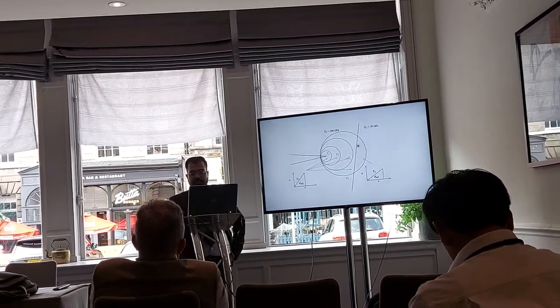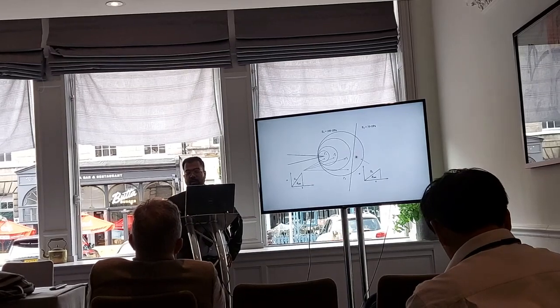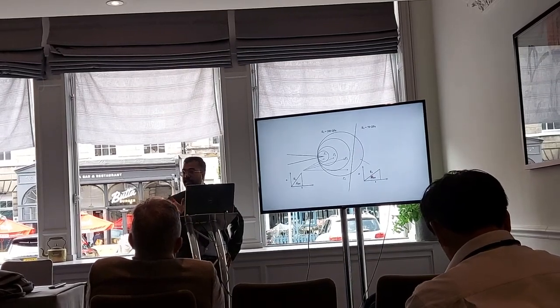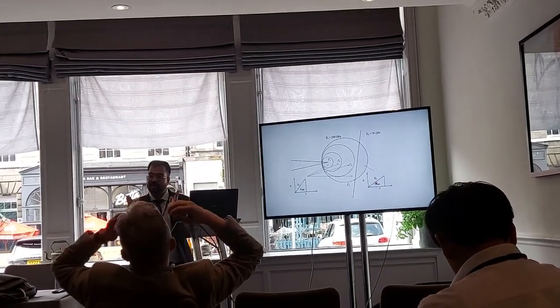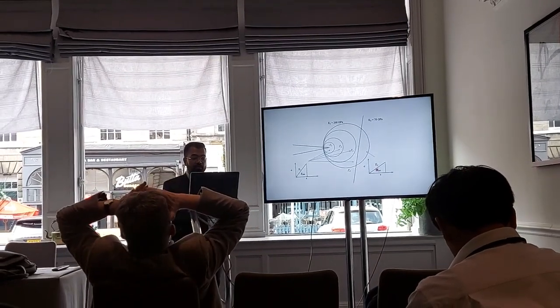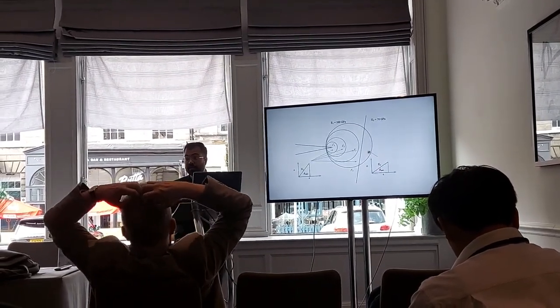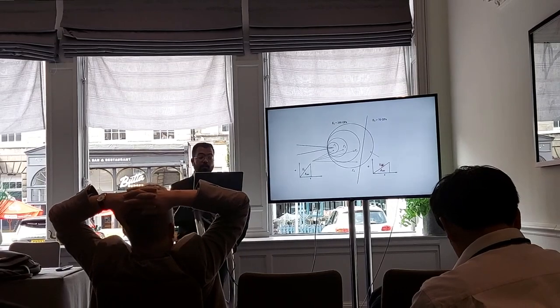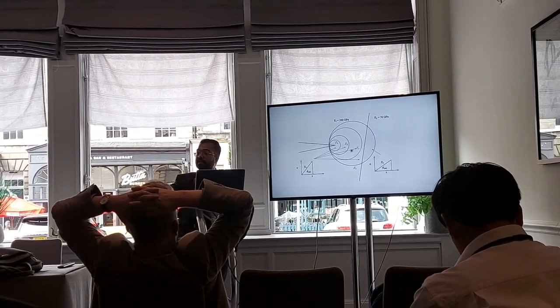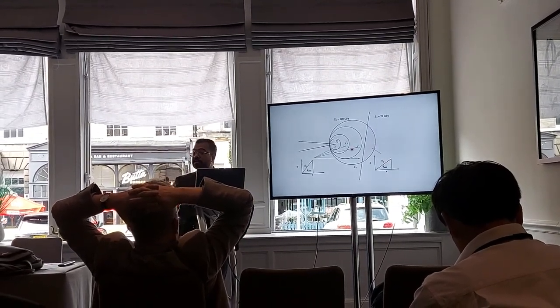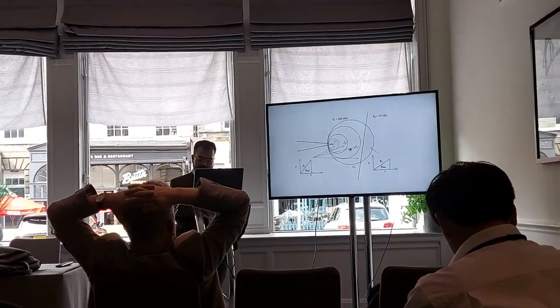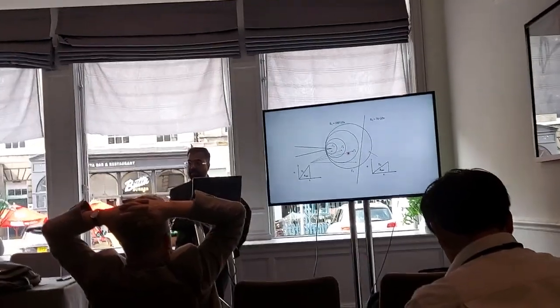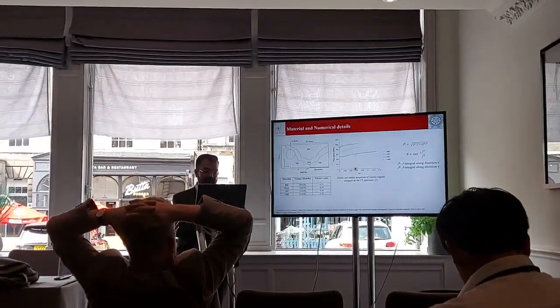But if you have an interface, then this part is deforming with a different elastic modulus, imagining that the difference is only in the elastic moduli. So this part will consume lesser strain energy density, more will be available on the left hand side, so the crack will have more energy to grow. So that's the idea of attraction and repulsion because of the interface.